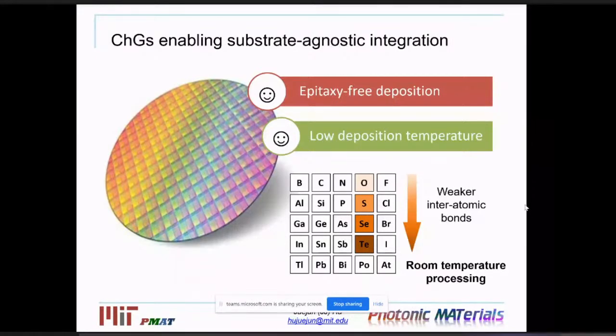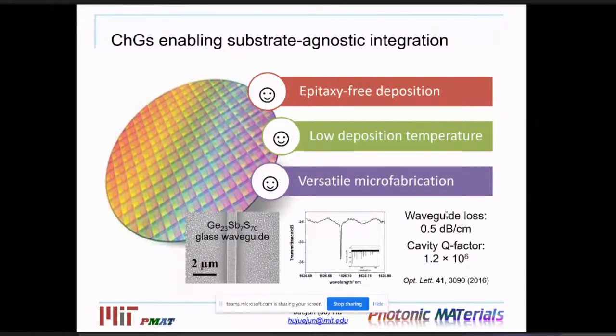This is also critical for integration of different substrates, because one of the biggest limitations is actually thermal stress. Thermal stress usually causes delamination and weakens the interface between the film and the substrate. With room temperature deposition, we can completely circumvent the issue of thermal stress and therefore get good adhesion between chalcogenides and a diverse range of substrate platforms. Of course, like I said, we can also fabricate these components from chalcogenide glasses using well-established microfabrication techniques. As one example, we can fabricate waveguides with low propagation loss and cavity quality factors exceeding 1 million in optical resonators. That's important for many applications.